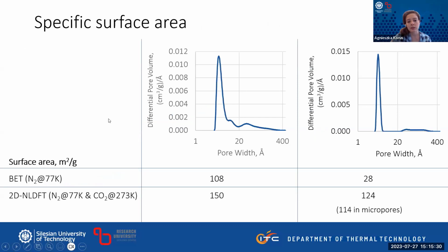We think this method is particularly good for working with microporous samples because the commonly used BET often underestimates the surface area of the sample. If it's a wider distribution, the difference is still significant. But if you use very ultra-microporous materials, you can see that because you don't use CO2, just nitrogen adsorption, the BET value is really low, and you can have quite a lot of surface area still hidden in the ultra-micropores of the samples. So we chose this way to evaluate our samples.